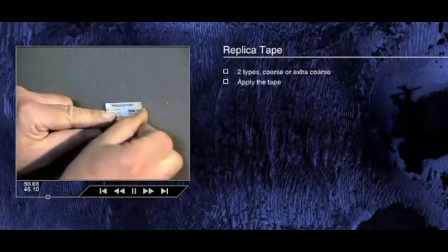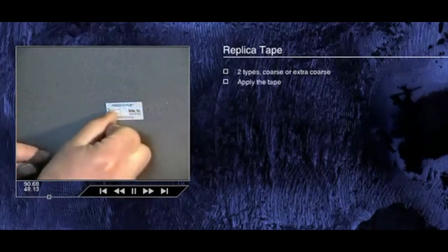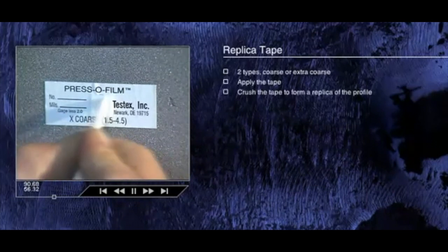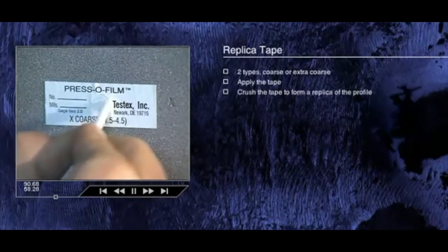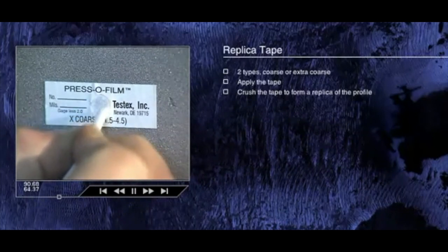A piece of tape with a small square of compressible foam plastic attached to a non-compressible plastic mylar film is applied to the blast clean surface dull side down. A hard, rounded object, a burnishing tool such as a swizzle stick, is then used to crush the foam to the blast clean surface, causing the foam to form an exact reverse impression replica of the actual surface profile.